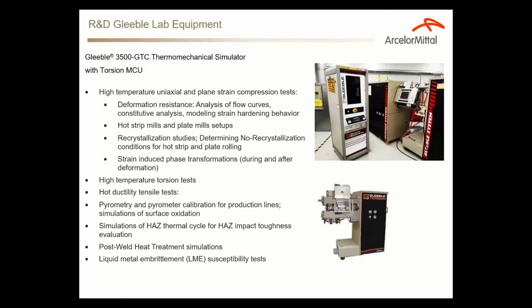setting up their rolling practices, and that includes recrystallization studies, of course, and strain-induced transformations. High temperature torsion tests, we also run basically for plate applications, hot ductility tests for casting applications. We also use quite extensively pyrometry, pyrometer calibration, simulations of surface oxidation.